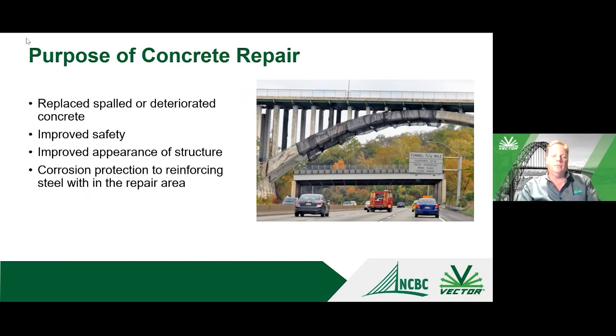So we talk about concrete repair. Obviously, if you're on this webinar, you're interested in the subject, and unfortunately, I probably spend too much time driving underneath bridges and looking up at the condition, particularly of concrete, which is my interest. But what is the purpose of the repair? You see visual damage. This is a photograph of netting that's been placed on this arch bridge, basically trying to contain any type of concrete deterioration or spalling. So we want to replace the spalled and delaminated concrete, and it's going to improve the safety. It's going to improve the appearance of the structures. And if we follow the right, proven procedures, the repair itself will be durable and will provide protection to the reinforcing that is actively corroding in the repair area.